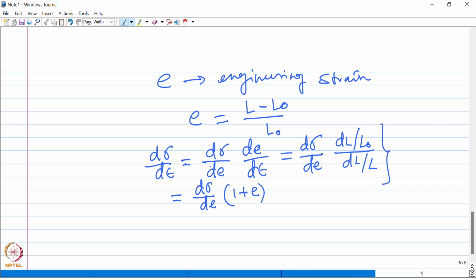And this whole thing is equal to 1 plus E. If we reorganize this, you would end up with this 1 plus E, right? And this is equal to sigma according to the instability criterion, right? So this gives us d sigma by dE equals to sigma by 1 plus E. And this gives rise to an interesting construction if the true stress is plotted against the engineering strain. Okay, so if that is done, the curve will look like this.